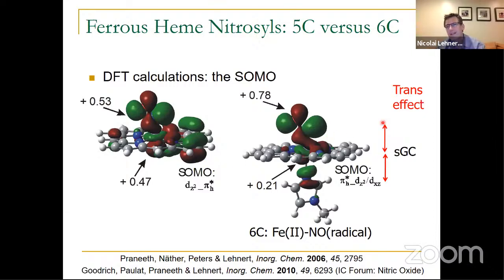You can also think about the trans effect as a competition. We have the dz square orbital here, and we have two ligands, NO and our imidazole, and they compete for binding to dz square. NO makes the stronger bond, so it ends up in the bonding combination, but the imidazole makes the weaker bond, so it ends up in the antibonding combination, and that weakens that bond.